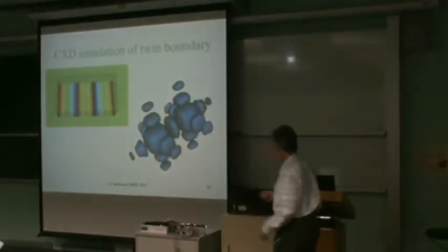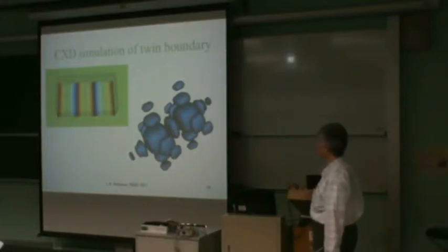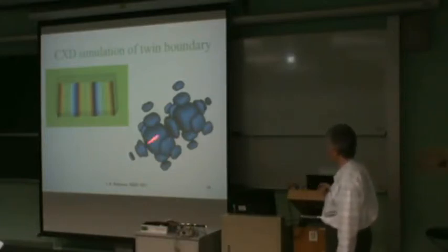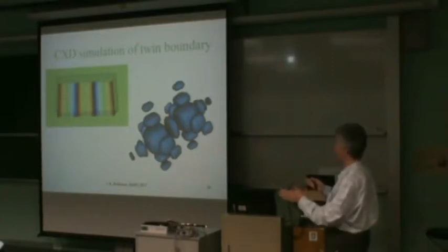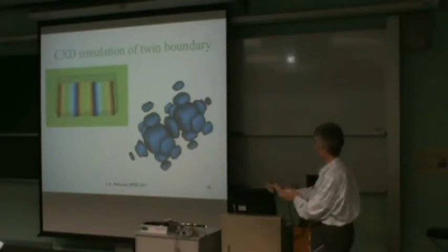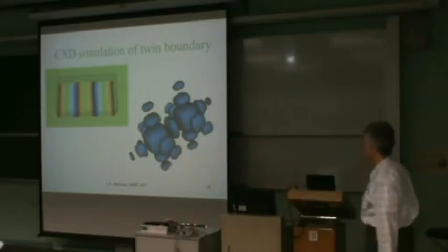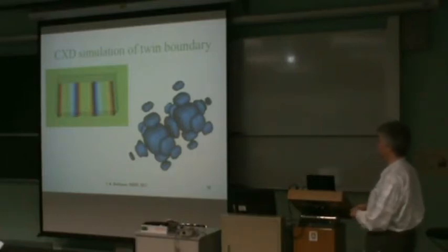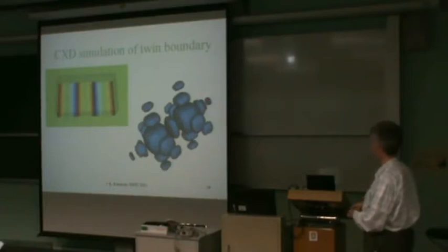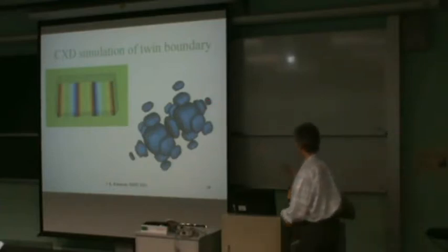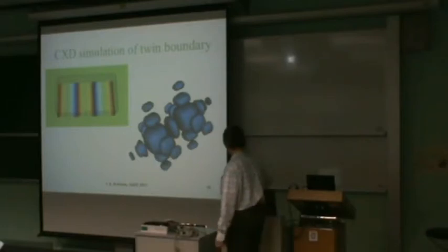This is the calculation that goes with the image I showed before, and you should expect to see two Bragg peaks and a set of fringes that would be tied to those two Bragg peaks. And if it's as simple as just a block of material with a twinning plane down the middle and two oppositely distorted regions of tetragonal crystal outside it, you would get a symmetrically split Bragg peak like this. But our case is much more complicated than this, and you can't really tell.